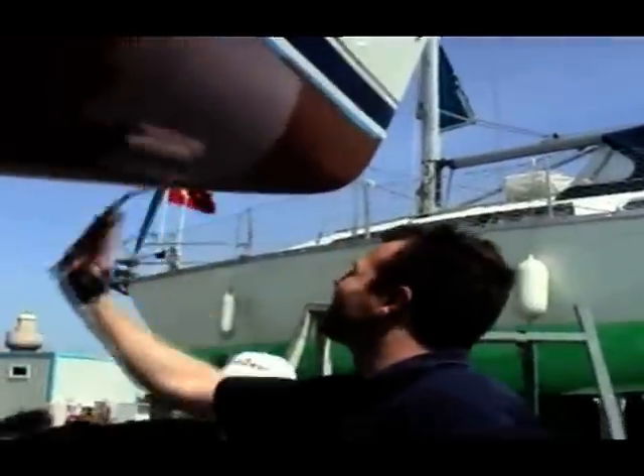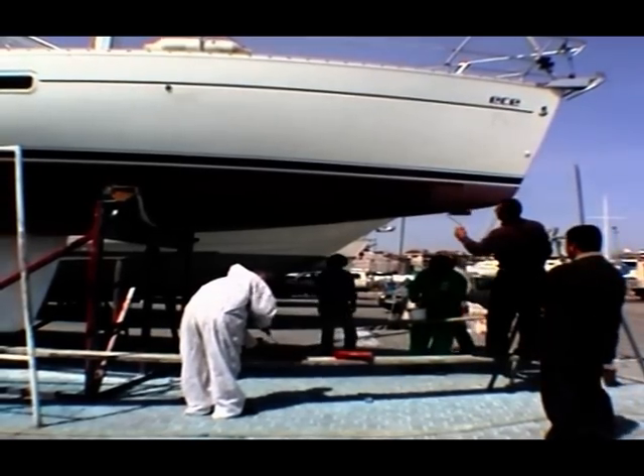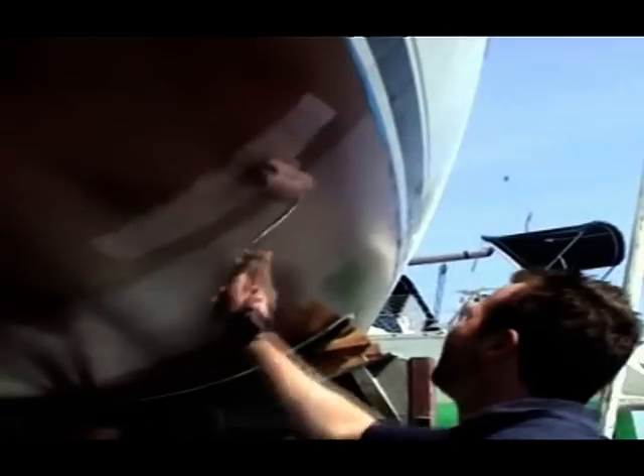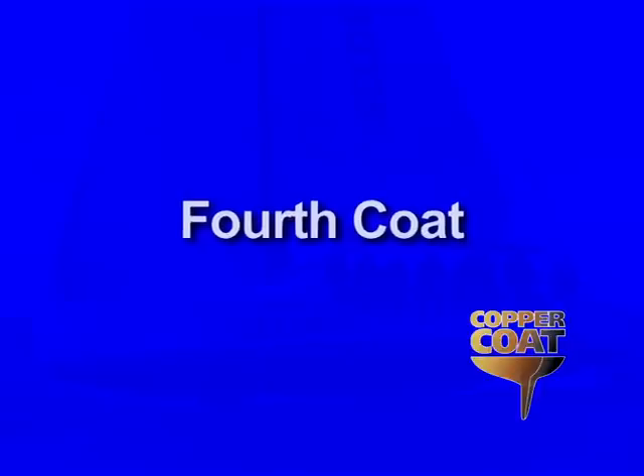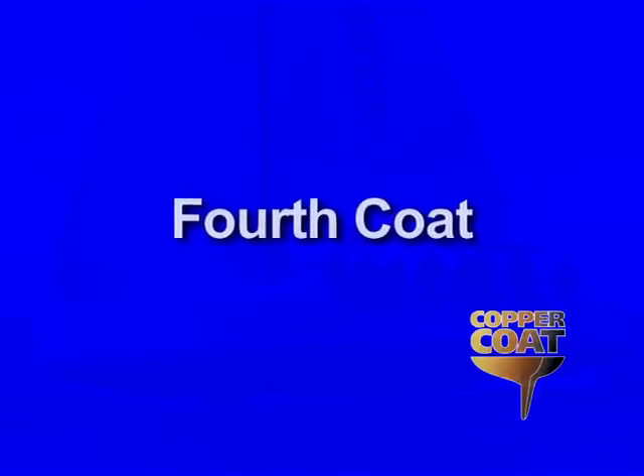As the coating's thickness builds, the gel coat becomes barely visible and the patchy appearance lessens. Occasionally, the treatment can look complete after just three coats, when in fact, a fourth is required. Usually, the treatment is completed with a fourth coat. By this stage, the coating appears thick, glossy, and deeply copper-rich.